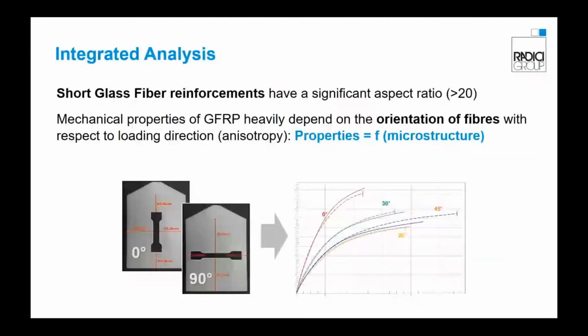Previously, we talked about the integrated approach, so an advanced type of simulation that takes into account the process-induced properties in the structural simulation. But why does it have a fundamental importance for metal replacement projects which involve reinforced plastics? Generally, reinforced plastics show an anisotropic behavior given by the orientation of the fibers, which have a significant aspect ratio. So different orientation of the fiber with respect to the direction of the load means different mechanical response of the material, as we can see from the right picture. In conclusion, we can say that the properties are a function of microstructure.